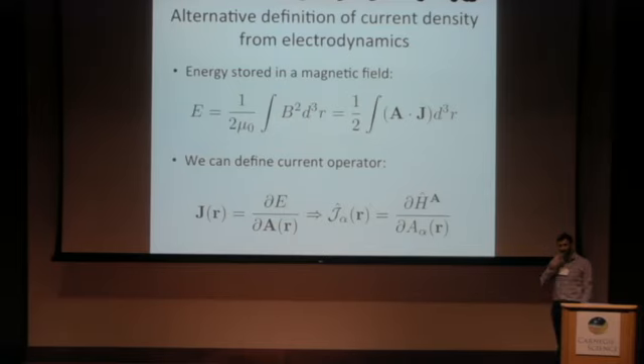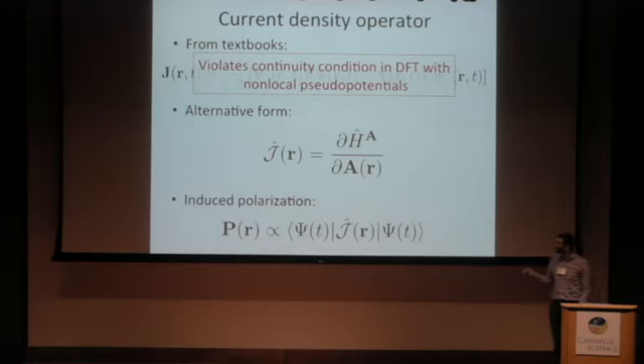So the way that we obtain this alternative definition is, again, from classical electrodynamics. We know that we can write the energy stored in a magnetic field in the following way, and we can relate this to a product between a vector potential and the current density. So here we have a relation between the current density and the energy, and so we can use that to develop a quantum mechanical operator, a current density operator, that is the derivative of the Hamiltonian in the presence of a vector potential, which will describe our photon perturbation, the derivative with respect to the vector potential. And so I won't go into any details of how we actually calculate this. You could ask me after the talk. But this definition of the current density actually satisfies the continuity equation and gives a physically meaningful value for the current. So the induced polarization is something like a matrix element with this current density operator.